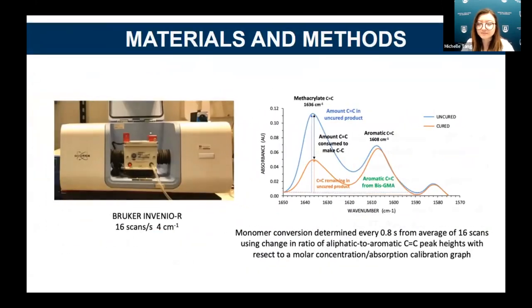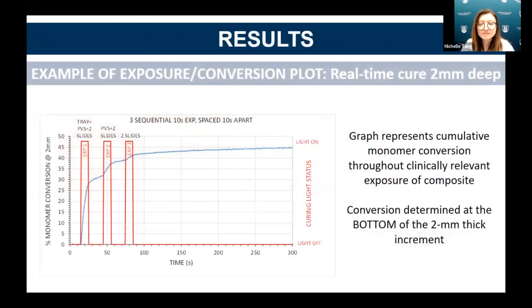aliphatic carbons. To illustrate the obtained data, for a 2 millimeter thick PVS material, a time versus percent monomer conversion chart can be formed. The blue line graph represents total monomer conversion, and as the setup was exposed to light, as shown in red, a drastic increase in percent conversion was seen. Data was taken for a total of 5 minutes for maximal composite cure.